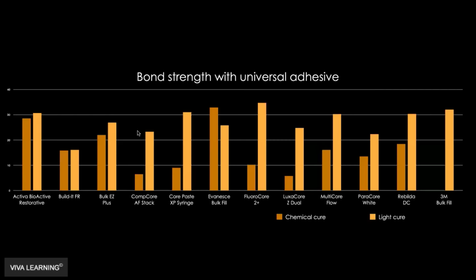So what you could see is there's some of these materials, when you let them cure in their chemical cure mode, which is the dark bar, they had not good bond strengths if you chemical cured them. So that's like if you had a dual cure material, like a dual cure buildup material, but you light cured it, things could be okay. But if you relied on its chemical cure mechanism, then it didn't have a good bond with the underlying bonding agent, and so essentially the bonding agent that's on the tooth.